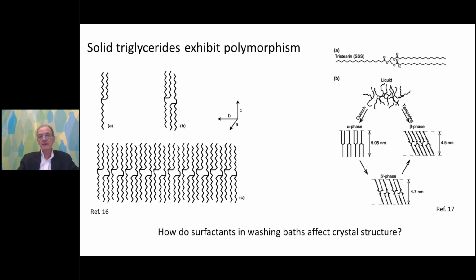So if we start off with something like tristearin from a liquid and we quench cool it, like what happens if you're frying something and you have a nice grease splatter, or that hamburger juice gets on your shirt because it's warm, right? If we quench cool tristearin from the melt, it forms the alpha phase, and that alpha phase is thermodynamically not stable. It's going to change and anneal over time to the so-called beta prime and beta phase ultimately. In those phases, the acyl chains are a little closer together and more tightly packed and tilted a bit. And so there are significant changes in the intermolecular interactions in those phases of the triglyceride as it anneals.